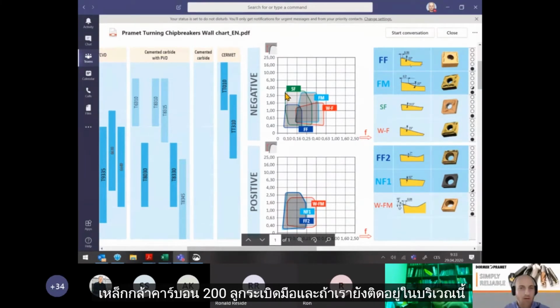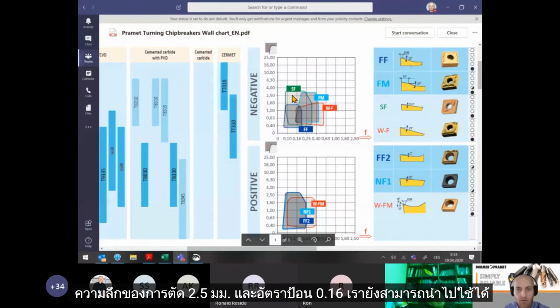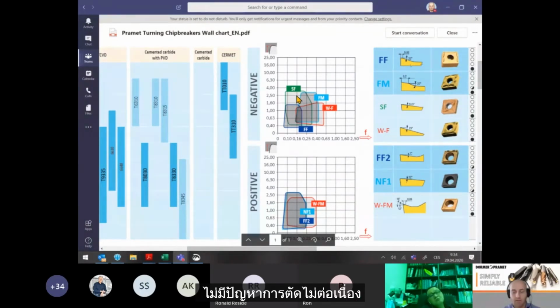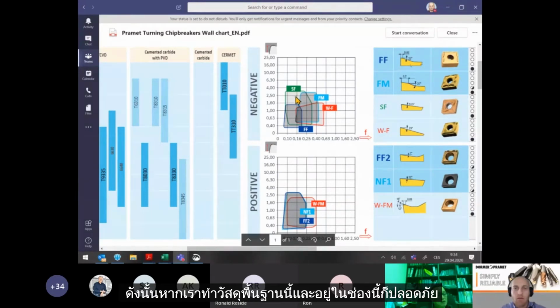So for example, if we use the SF chip breaker here for the reference material, carbon steel with 200 Brinell, and if we still stick inside this area that's highlighted here in green, so for example depth of cut 2.5 millimeters and feed rate 0.16, then we can still apply the values that are in the catalog or on the box, meaning the cutting is not interrupted. There is no problem. The cutting is continuous. There are no troubles with the machine or clamping. It's a stable process, and we can run it simply all the time. So if we are doing this basic material and we stay inside this field, it's safe to use the basic conditions.